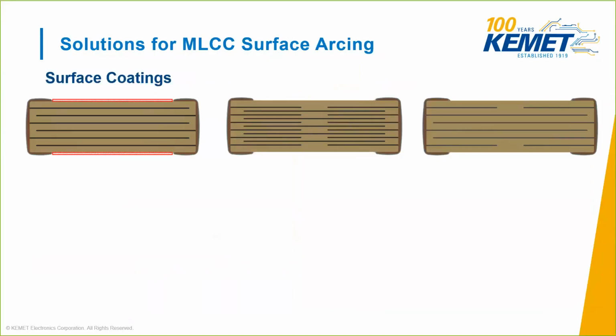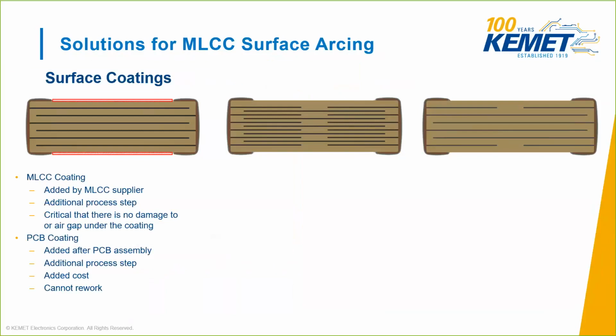One, suppliers have used surface coatings, and this is added at the supplier, not the end customer. It adds an additional process step, and it's really critical that there's no damage or air gap underneath the coating. You can also do PCB coatings added after the PCB assembly. It does add a process step and adds cost, and really once you apply that coating, it's very difficult, if not impossible, to do any real rework on the PCB.